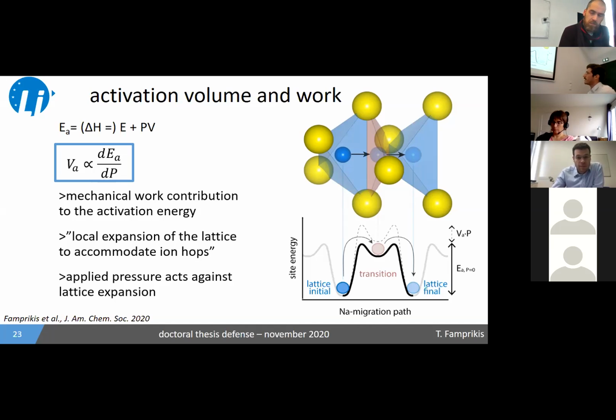So I don't have a direct answer to that, but the Grüneisen parameter that I'm referring to here is not, I should say, the overall Grüneisen parameter of the material, something you would, let's say, quantify with the heat capacity and the speed of sound and so on. It's the mode-specific Grüneisen parameter. You can define a Grüneisen parameter for each mode specifically, and here we're interested in the mode that actually carries the ion over the transition state. So I guess the anharmonicity of that mode is what's important, but deeper than that, I'm not sure I can go at this point.